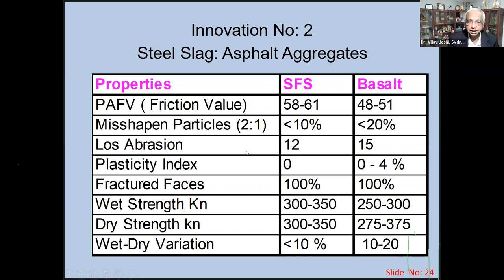But the critical portion is, if you see the misshapen particles, almost they are good. Loss abrasion is also good. There is no plasticity in the aggregates because it is manufactured at the furnace level. Wet strength, dry strength, I mean, it's absolutely steel furnace slag is good material compared to basalt. And particularly PAFV, which is the friction value. Now, if you see that 58 to 61 with the steel slag, while basalt is 48 to 51.